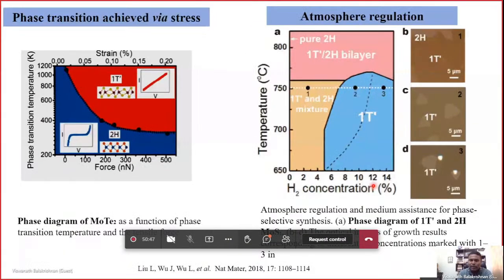There are two possibilities. One is during the cooling, right? You do a fast cooling so that kinetically you can control. And the other possibility is by changing the growth parameters. It is known that we typically use hydrogen in order to have a reducing atmosphere. With respect to hydrogen content also, it is known that the 1T prime or 1T metastable phases can be stabilized.